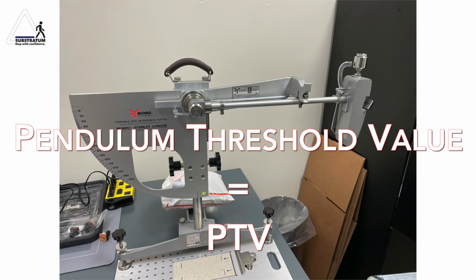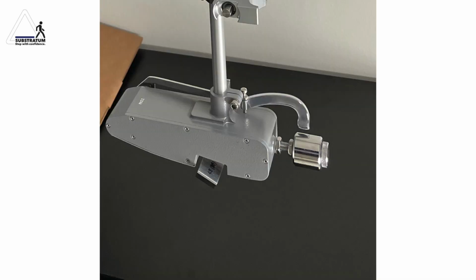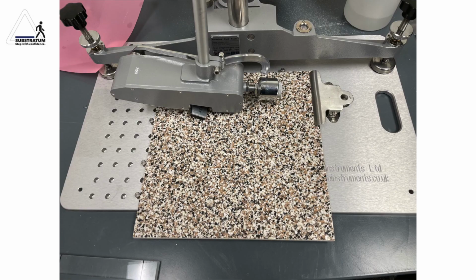For pedestrian walkway surface testing, the pendulum uses a 4S slider with a rubber hardness of 96. Once the pendulum has been verified prior to testing, materials can then be measured either in the lab or on site. If you sell flooring surfaces or apply coatings in Europe or Australia, it is the preferred way of measuring flooring materials for slip resistance.